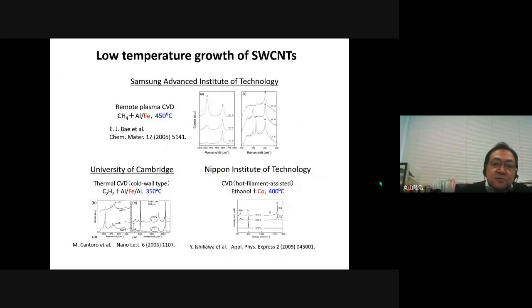Next, I would like to talk about single-wall carbon nanotube growth at low temperature. So far, several groups reported SWCNT growth at low temperature by CVD using iron or cobalt catalyst. Many groups reported SWCNT growth at 400 degrees C. Among them, University of Cambridge group attained SWCNT growth at 350 degrees C by thermal CVD. Next, please.